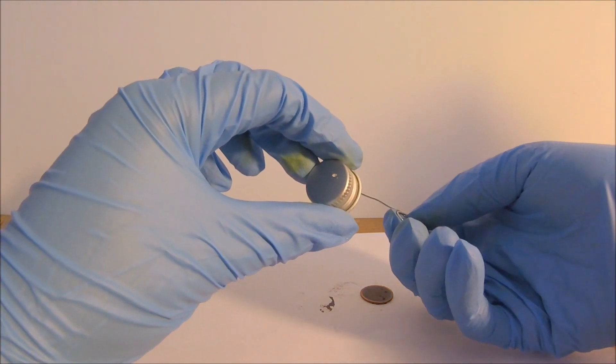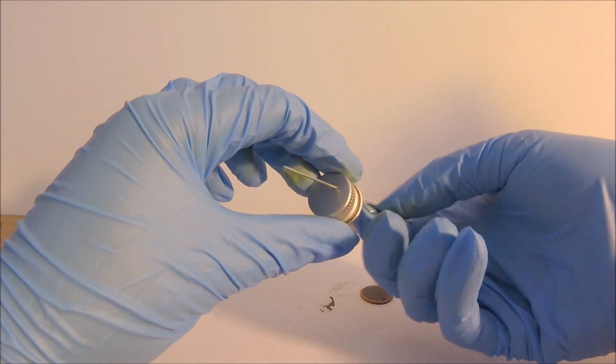What is interesting is actually the way it was corroded. So let's take a closer look at it. The corrosion mainly occurred at the hole and the surrounding part was left untouched. This is a typical pitting corrosion, where the corrosion was extremely localized.